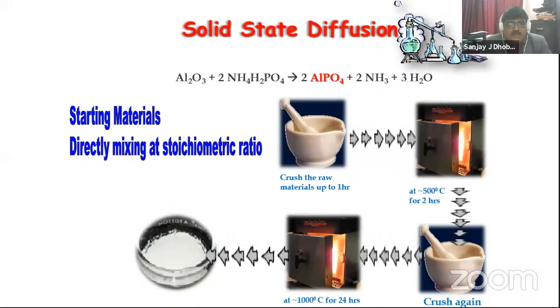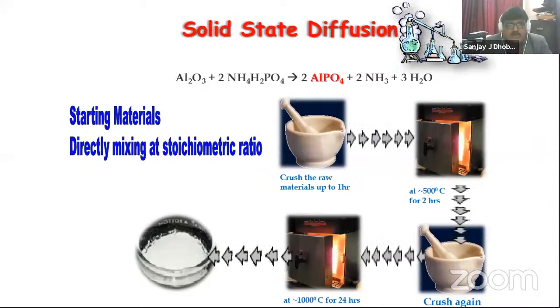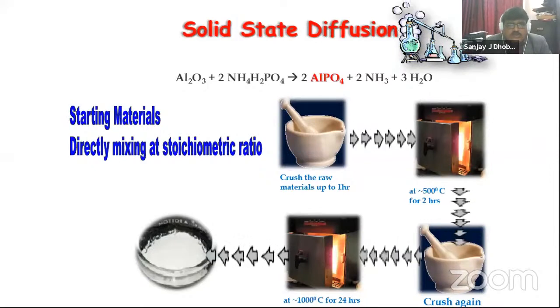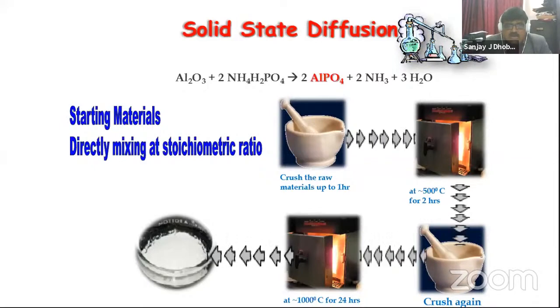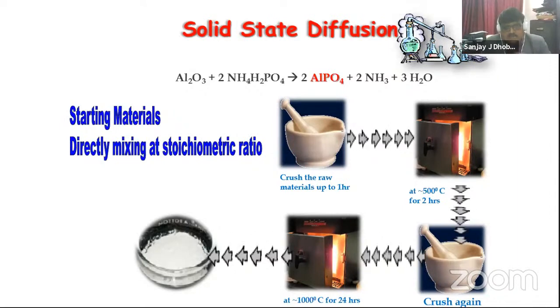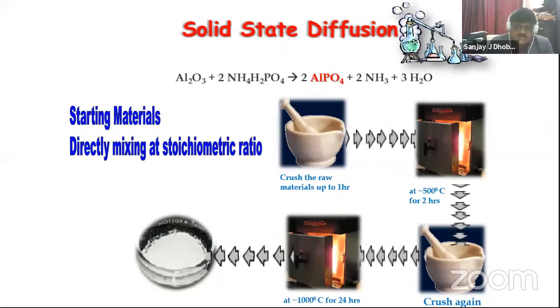The starting materials are aluminum oxide and ammonium dihydrogen phosphate in a particular stoichiometric ratio. You mix and crush for 1 hour, then put it in the furnace at 500 degrees centigrade for about 2 hours. Some of the water molecules evaporate, then it is cooled down and crushed again so that the diffusion process is proper, and fired at high temperature for 24 hours. This long time ensures proper diffusion, and the material is prepared.